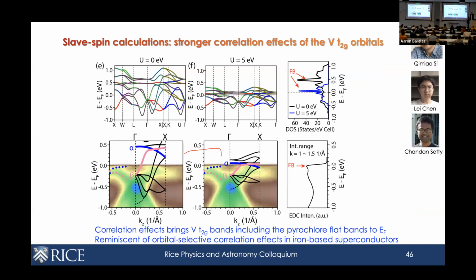So Qimiao Si's group did this calculation by carrying out slave spin calculations, and to make a long story short, by adding Coulomb interactions, they can bring the flat band down to the Fermi level, all the bands are renormalized, and it makes a better agreement with the data that we see.